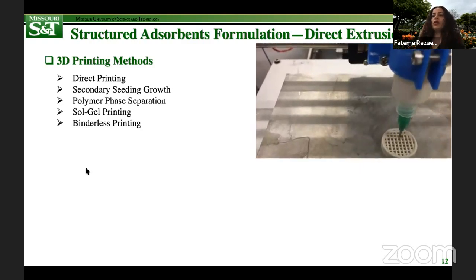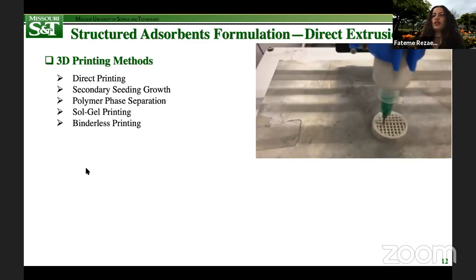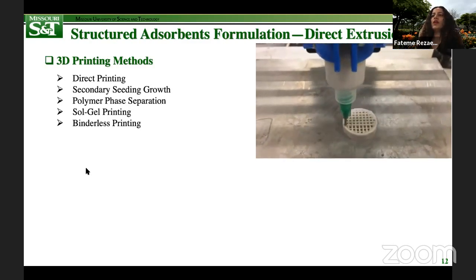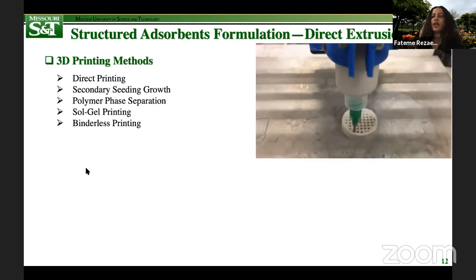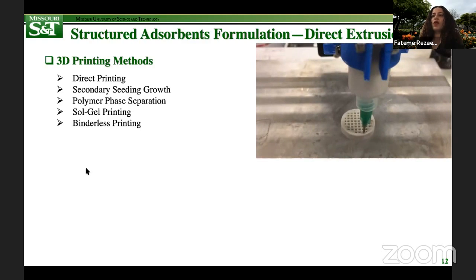We do have polymer phase separation, which is based on a phase inversion technique commonly used for forming polymeric hollow fibers through a spinning process, by which a liquid paste containing solid sorbent particles, solvent, and a polymer dope transforms into a phase-separated solid structure with nanoscale hierarchical pores. Sol-gel approach is another promising 3D printing method to shape adsorbents into robust structures with high adsorbent loading. It's also possible to shape engineer adsorbents into binderless structures using 3D printing approach, in a similar way as commercially available binderless sorbent beads or pellets.